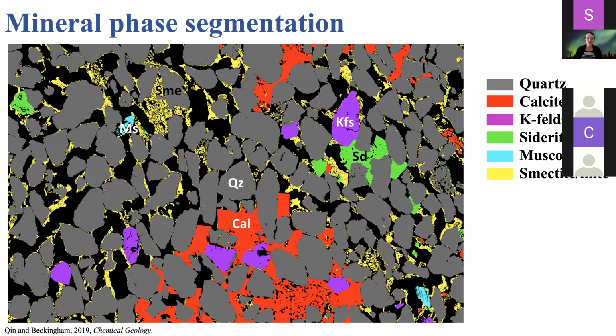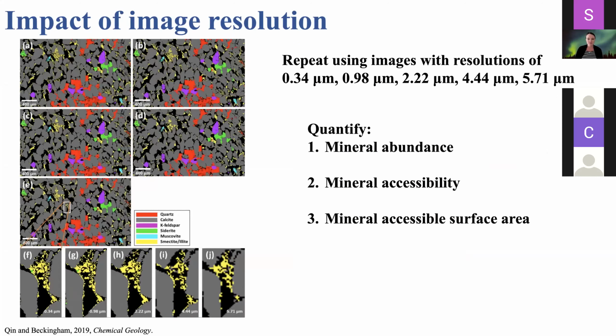And so this particular formation is really rich in quartz, but we also have some more reactive phases like calcite present, as well as some feldspars and clay minerals, or the clays are shown in yellow. We then repeated this process for images with resolutions from 0.3 microns to 5.7 microns, and then processed the images to quantify mineral abundances, accessibilities, and accessible surface areas.